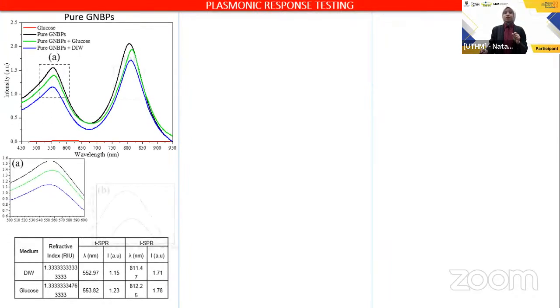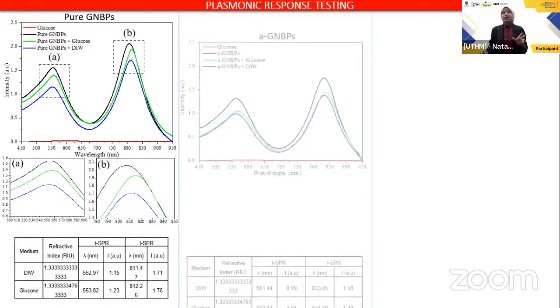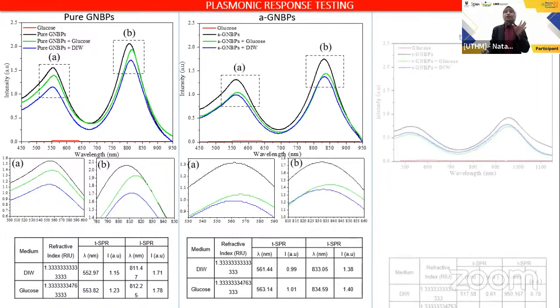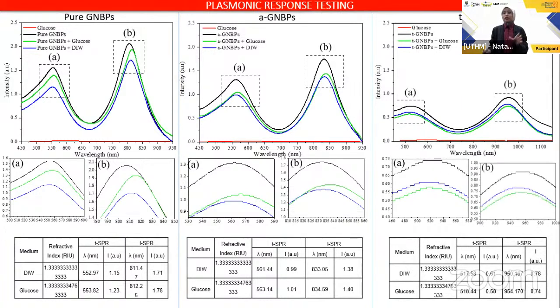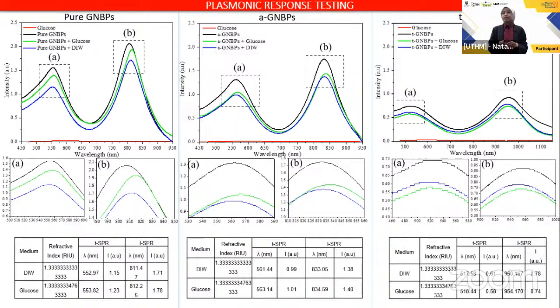Then, we want to know how gold nanopyramids perform when detecting glucose molecules. So we tested pure GNBPS, A-GNBPS, and the last one, T-GNBPS, for plasmonic response mechanism testing. Based on this test, pure GNBPS, A-GNBPS, and T-GNBPS can detect different media, denoted by intensity change and wavelength shift. Of course, we want to know the optimum time to functionalize the surface of gold nanopyramids so we can get the best signal response for our plasmonic sensor application.